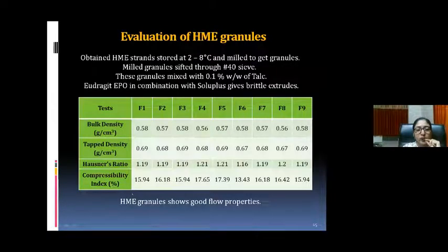The obtained strands are stored at 2 to 8 degrees Celsius and milled to get granules. These granules are sifted through a sieve so that we get a particular size range, and then the granules are mixed with 0.1% talc. Generally, we have used Eudragit EPO in combination with Soluplus. This gives brittle extrudates.